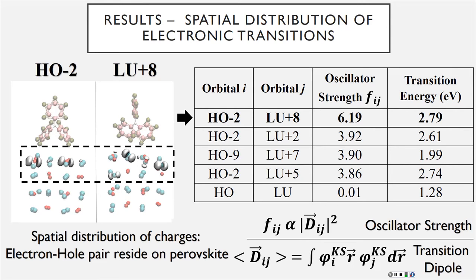So if we're looking at the spatial distribution of electronic charges, the right table shows the electronic transitions between orbitals I and J, so HOMO-2 to LUMO+8 state, and then the oscillator strengths for that transition, which gives the probability of that transition occurring, and then the transition energies for those transitions. So for this first one here, for the HOMO-2 to the LUMO+8, we can see that there's not much spatial charge separation because it basically just jumps into another region of the perovskite.